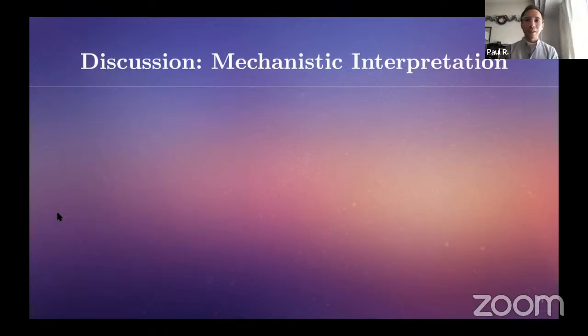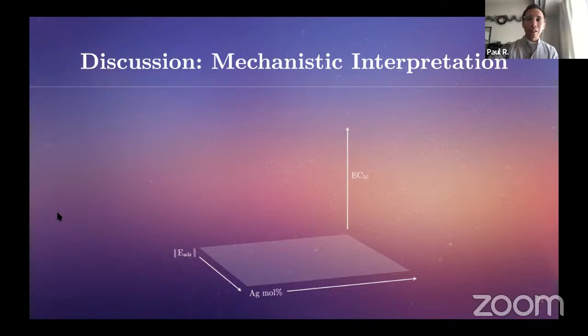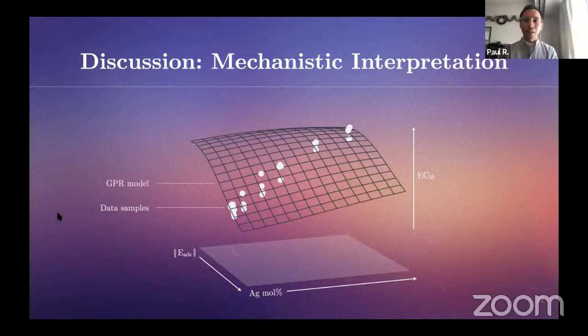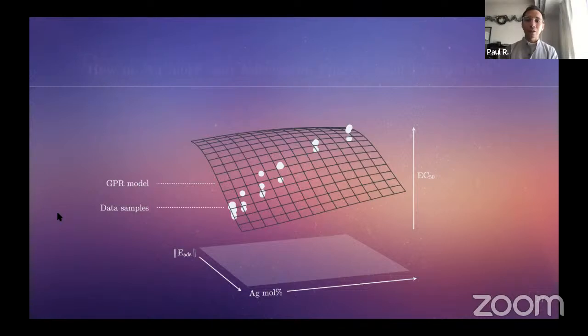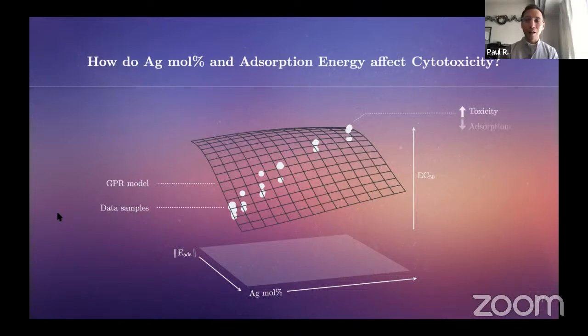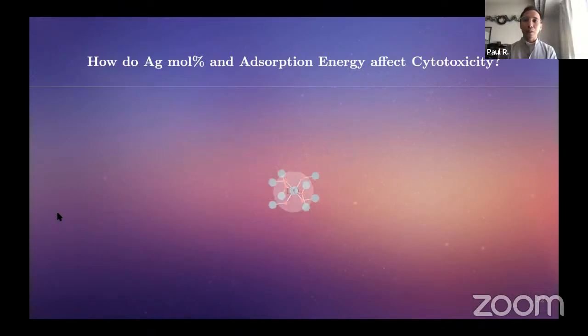Now, let's discuss the possible mechanistic interpretations of our results. By looking at the best features, Ag% and adsorption energy, and their relationship with EC50 toxicity, we can see that our model reaches higher toxicity values when adsorption energy is low and Ag% is high. To explain this effect, let's take a look at how metal mixed TiO2 nanoparticles react when mixed into CHO cell solution.